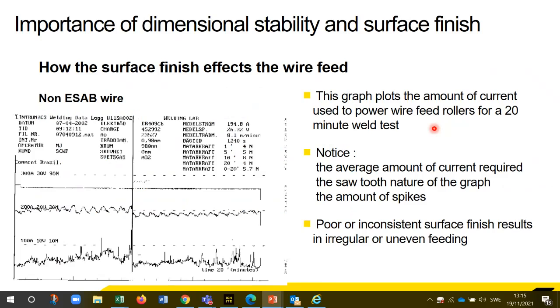This is an illustration of the surface finish effects of the wire. So this graph is plotting the power, the amount of amps taken by the drive rollers on a wire feed unit. Okay. What you can see, notice, the average amount of current required is quite high, and there's a lot of spikes. There's a lot of variation. So that means that the surface finish of this is taking a lot of power, less power, a lot of power. So the surface finish varies across that. So it's inconsistent. So you're not going to get a nice, smooth, consistent feeding.